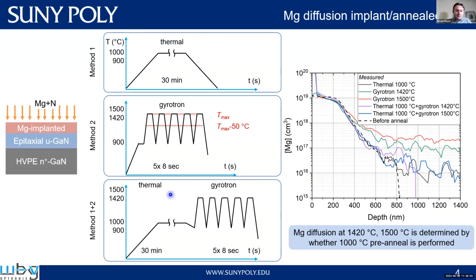So I studied this diffusion process by implanting GaN with magnesium and annealing it with either a moderate temperature anneal, an ultra high temperature anneal, or by a combination of the two, and then studied the diffusion behavior of magnesium using SIMS here at CNSE. And I found that this use of a pre-anneal strongly affects the diffusion of magnesium into the material.